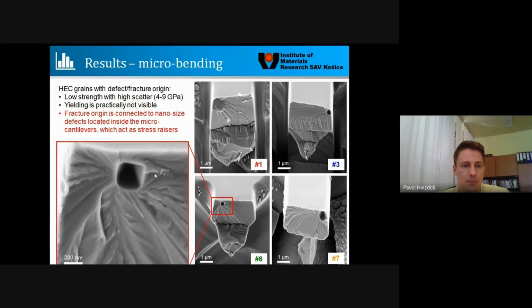Here we can see the fracture origin. It's connected to a nanosize pore, and most probably close to the nanosize pore there should be some crack as well, but due to the low resolution we were not able to resolve that.